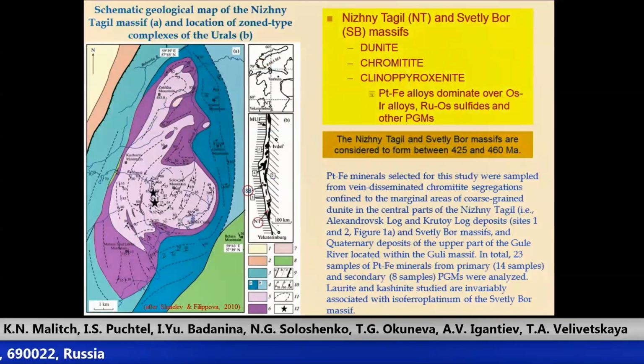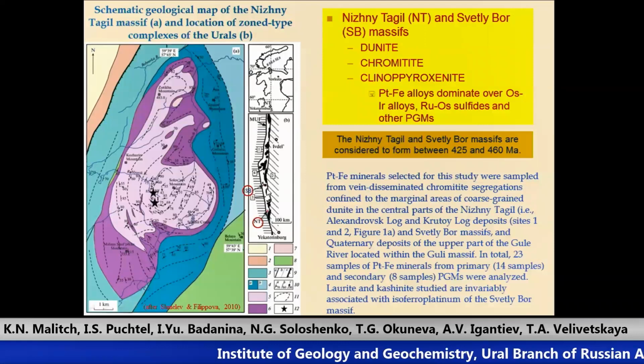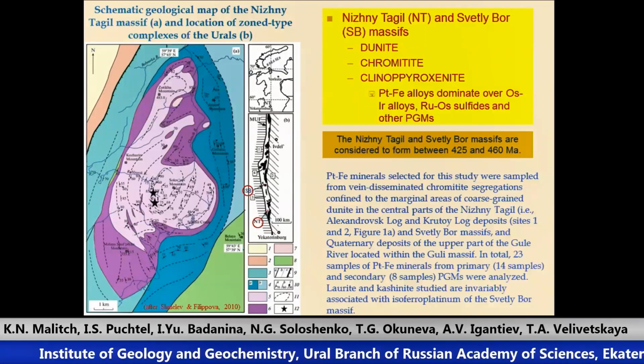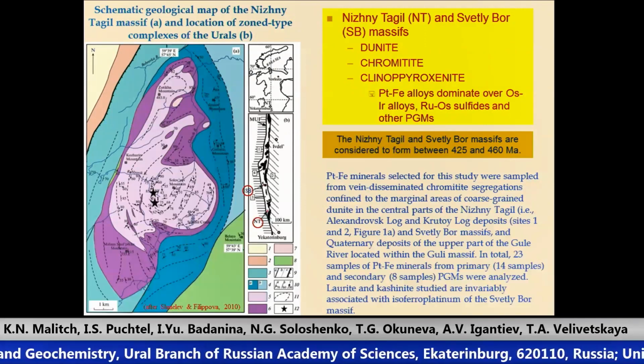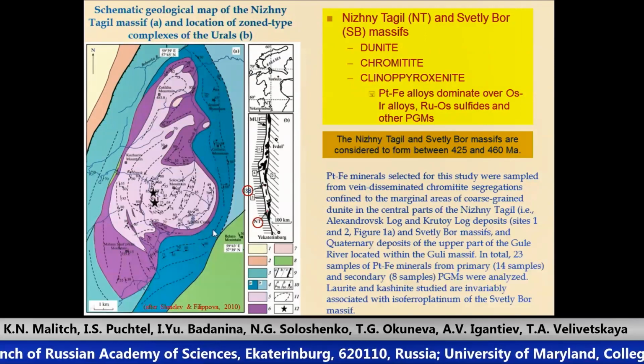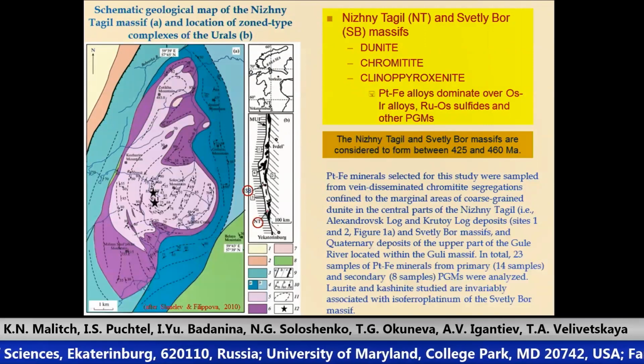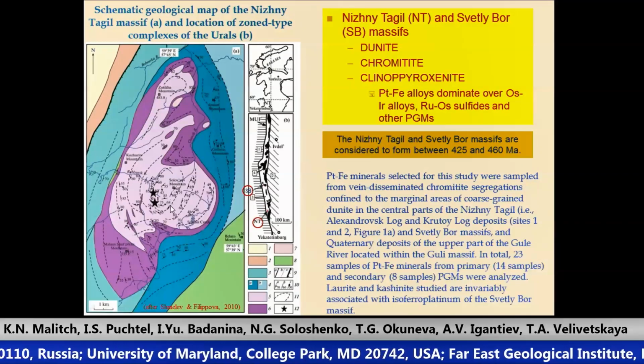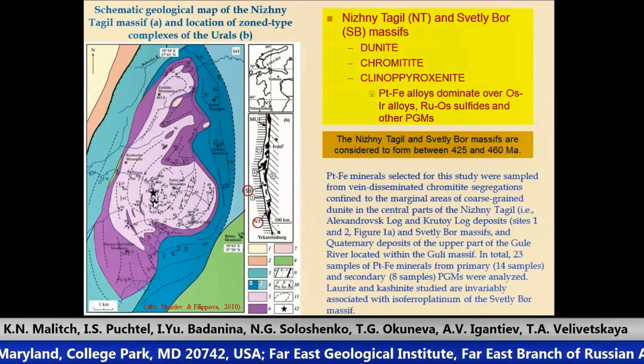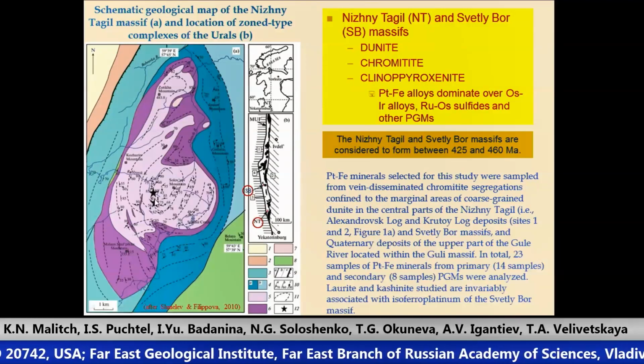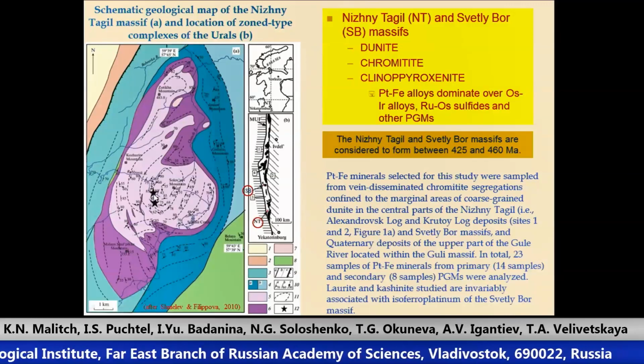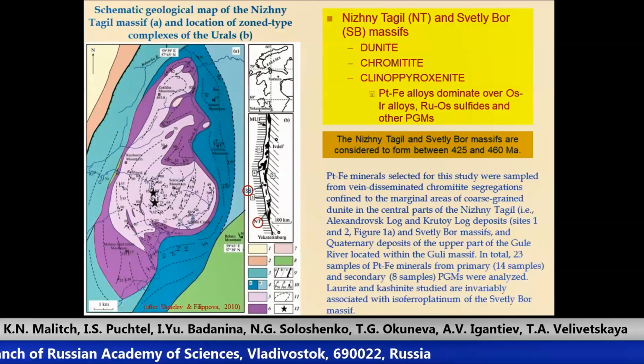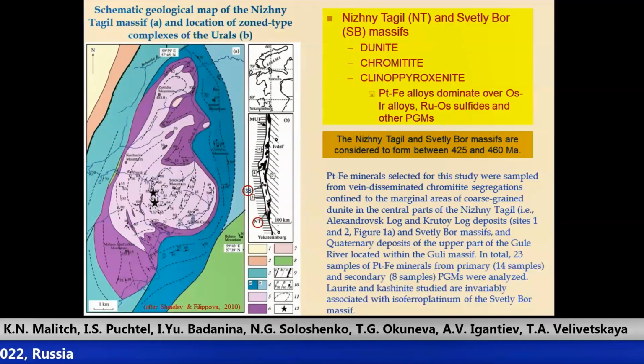The Nizhny Tagil and Svetly Bor zoned massifs form part of the platinum-bearing belt of the Urals, which is located along the 60th meridian for more than 900 kilometers. Platinum iron minerals selected for this study were sampled from vein-disseminated chromitite segregations confined to the marginal parts, areas of coarse-grained dunite in the central part of the massif, and are restricted to the Alexandrovsky Log platinum deposit and Krutoy Log platinum deposit. Also, other minerals derived from similar geological settings at Svetly Bor and placer deposits within the Guli complex.